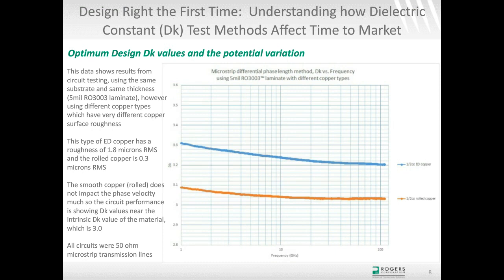Still very good, though. And what you can see is the smooth copper, even though it's thin and these copper planes are close together, the smooth rolled copper, the orange curve, is pretty close to the intrinsic dielectric constant of the material at 3.0. That's because the very smooth copper is really not slowing the wave down. The blue curve with the rougher copper is slowing the wave down. And again, a slower wave means higher dielectric constant.